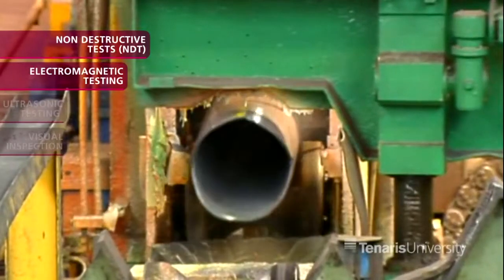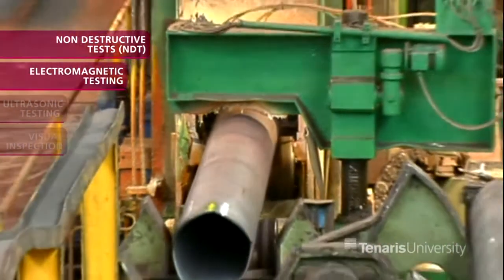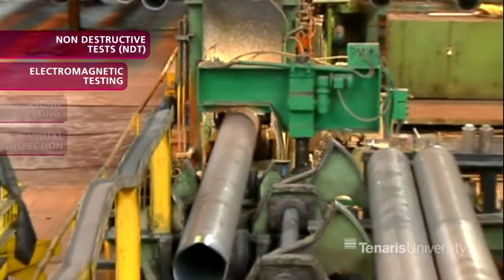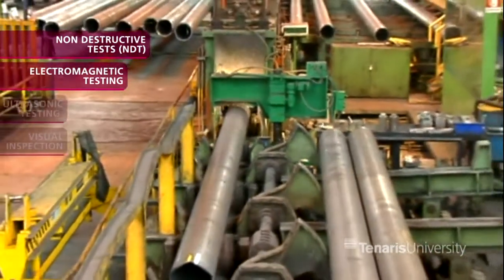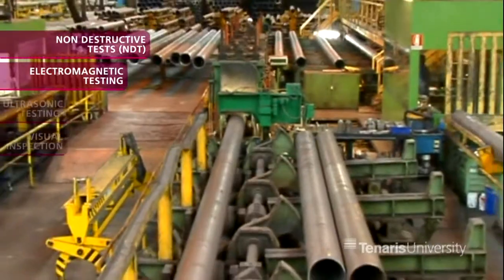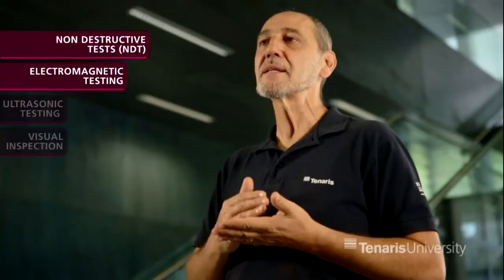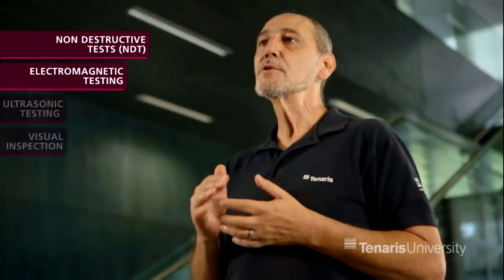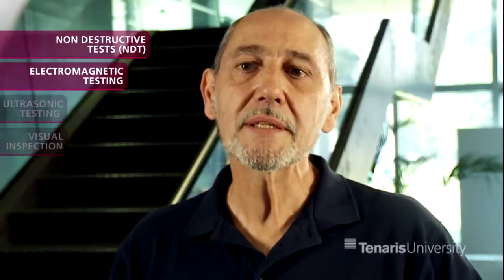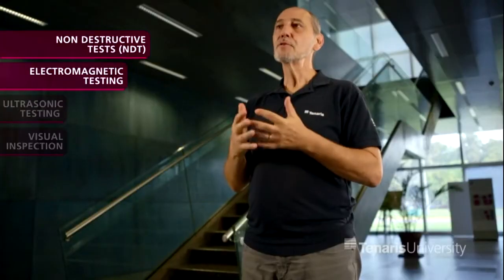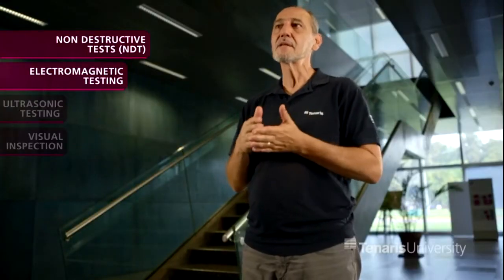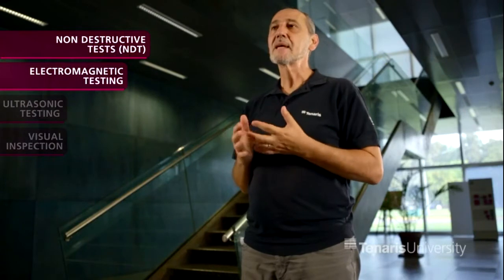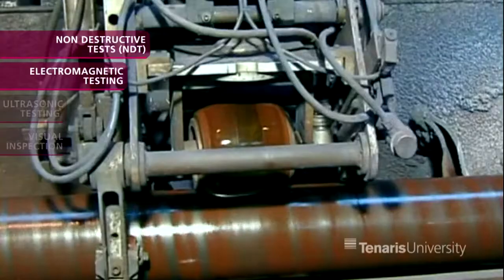The tube is transverse or longitudinally magnetized according to the type of defects to be detected. Defects generate dispersion in the magnetic flux, which induces electric signals in the equipment sensors as it travels through the defect area. If the tube shows defects, it is sent to a prove-up table. Then it undergoes a dry magnetic particle inspection.